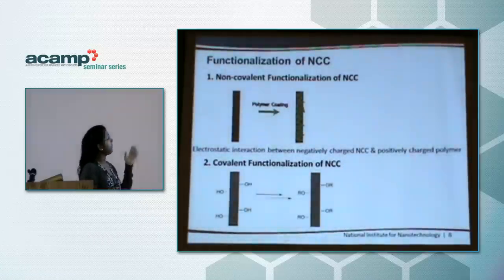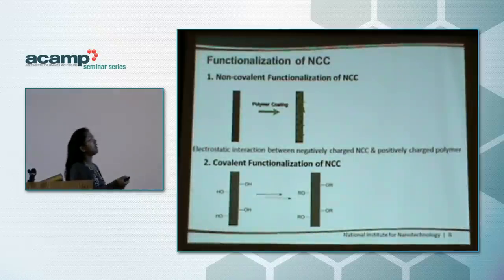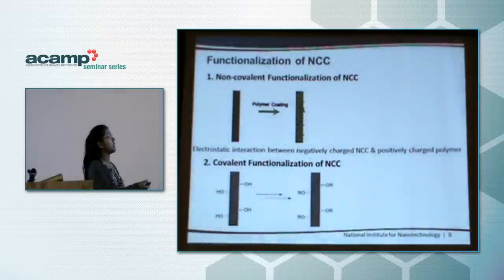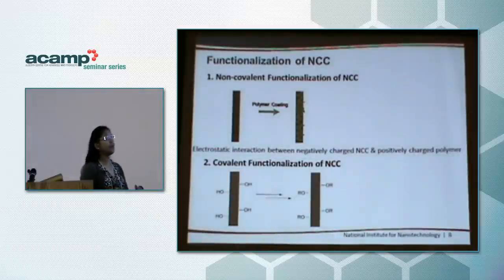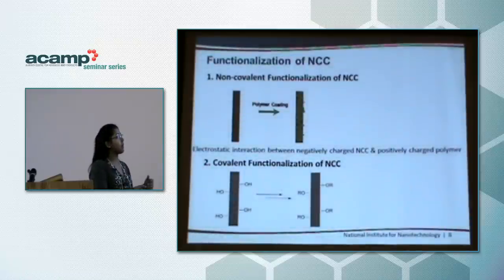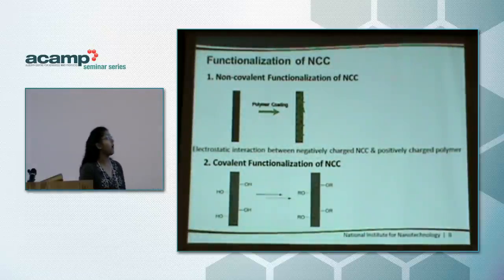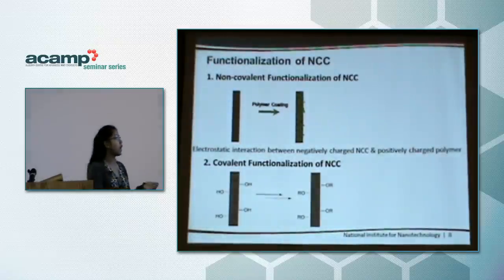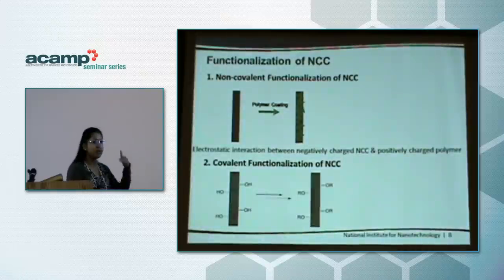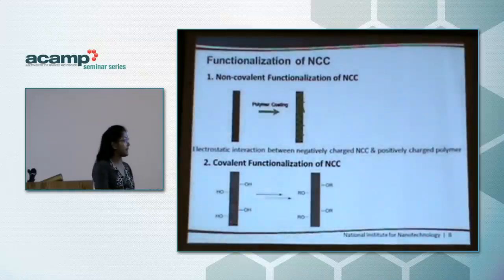The first approach is non-covalent functionalization, where we wrap a polymer onto the NCC rod surface. This polymer is held onto the NCC surface by electrostatic interaction between the negatively charged NCC and a positively charged polymer. The second approach is covalent functionalization, where we do chemistry on the hydroxyl groups present on the surface of NCC to modify it.